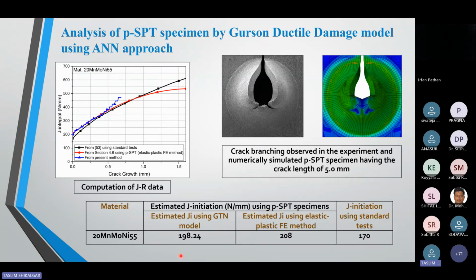And this is estimated using the Gurson damage mechanics model, and this is predicted from the elastoplastic FE simulations, and this J initiation data is available in the literature. That is possible because this is the plane strain fracture property, and this is the plane stress fracture property, and plane stress fracture properties are always greater than plane strain fracture properties. So this property is also useful. With the help of minimum material, you are getting exact properties near to the standard properties. I also published this data in the literature.